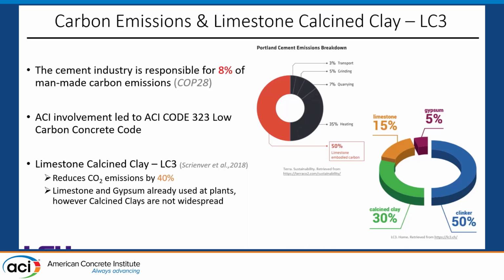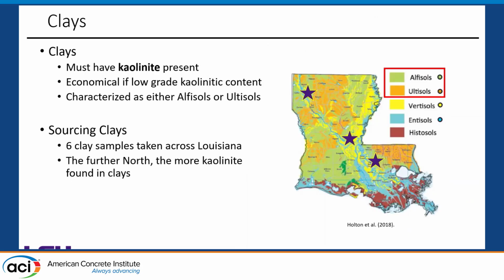It works off a new type of mix design that you can see in that photo to the right that replaces some of the clinker that's usually used in an OPC mix with both calcined clay and limestone. So first, for the clay that's used, you can't just get any clay from the ground. It must have the specific mineral called kaolinite present in it. This is the most reactive material found in the clay, and that's what's most important.